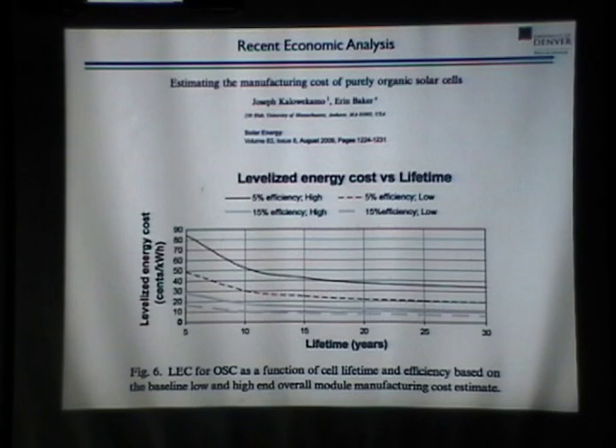And just to go through the numbers a bit, if you have a 5% efficiency device with a 20-year lifetime, then you're at about 37 cents per kilowatt hour. But if you have a 15% efficiency device at a 20-year lifetime, then you're at about 12 cents per kilowatt hour. So that gives you an idea of our target goal for the field: something like 12 to 15% would be sufficient to really compete head-on with fossil fuel-derived electricity. So again, LCOE, that's a good measure of economic performance.